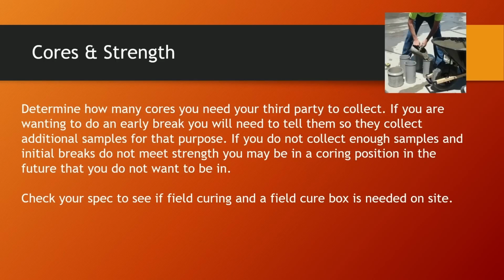Check your spec to see if field curing or a field box is needed on site. I would say 50% of the time they need a field box and they need to field cure. If that is the way your spec is written, then you have to make sure that they bring that field box and they have it set before pour day and that they don't take off with your samples. You don't want your samples right in the back of the truck back to their lab when it's supposed to be curing in your field box. So check that beforehand. And only because I've screwed it up.